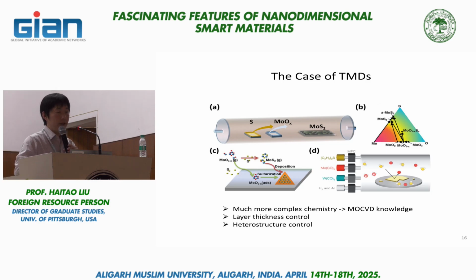But nevertheless, there's a significant effort put into the CVD growth of TMDs, in part because this class of material is very interesting in terms of electronic and optical properties. So they have a very bright future in the nanoelectronics industry. So at this point, people can grow wafer scale TMDs, 6-inch wafer, 8-inch wafer, single layer control, and even beyond that, heterostructures, and some examples I'm going to show in a sec.